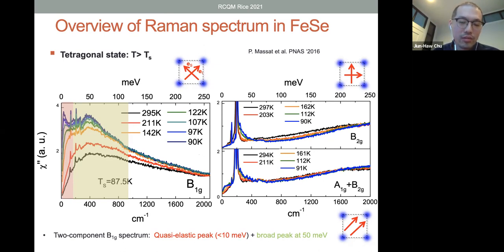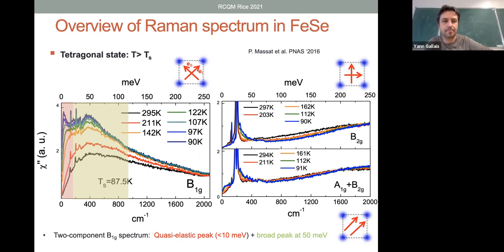And then there's also recent work on mapping the phase diagram from the iron selenide side to the iron telluride side. And it looks like there's a continuous suppression of the nematic phase transition. And there's actually an enhancement of the superconducting critical temperature that is different from the sulfur-doped iron selenide. So that would be an interesting system to study. Yeah, I agree. Thank you.